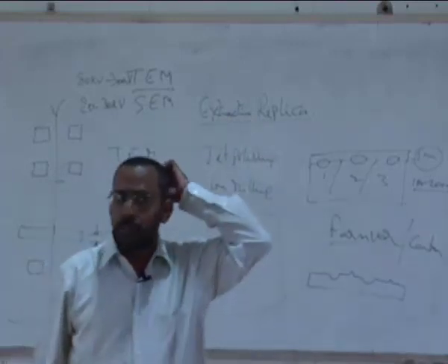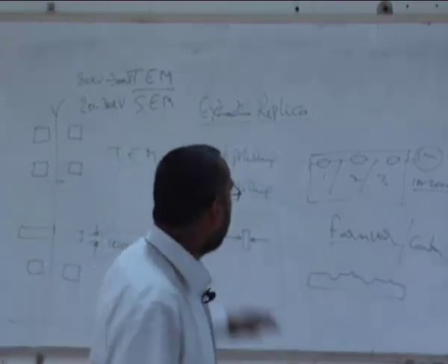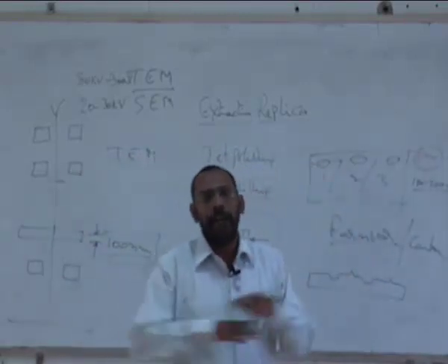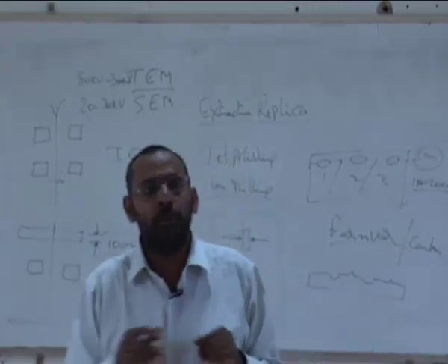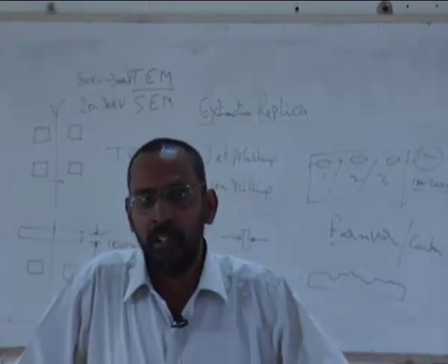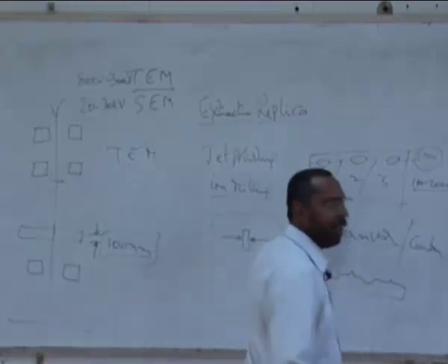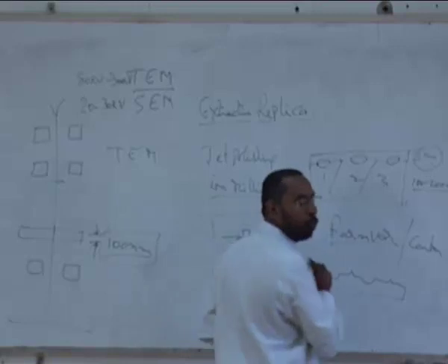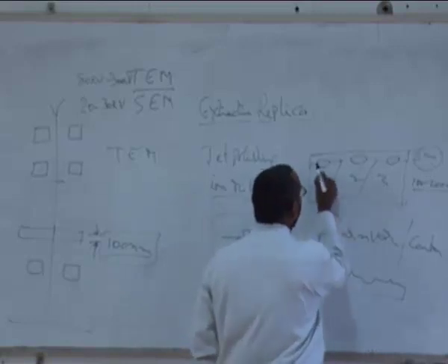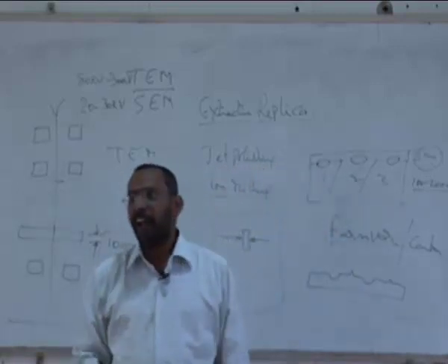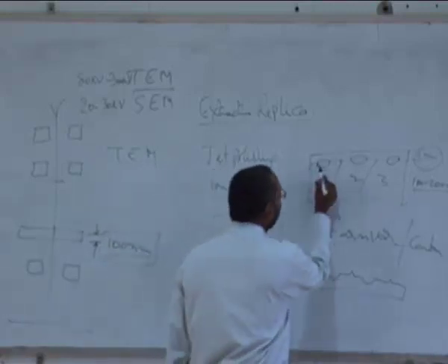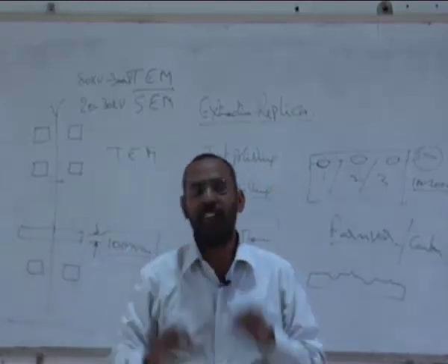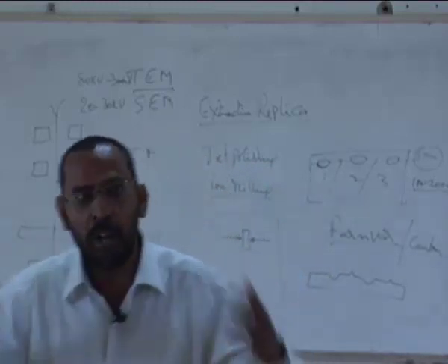What they used to do is a deep etching of the surface before this deposition. That means putting on a concentrated etchant and etching for a longer period, so that the particles at the interface between the matrix and the particle get attacked by the etchant. As a result, these particles start getting loosened and sit on the surface as loose particles, because you have etched them away.